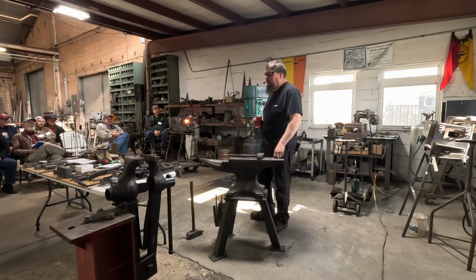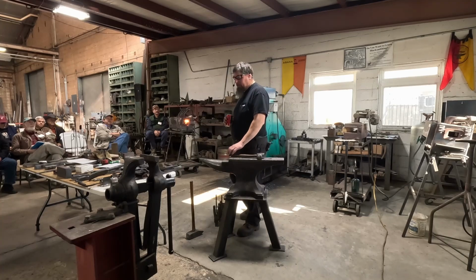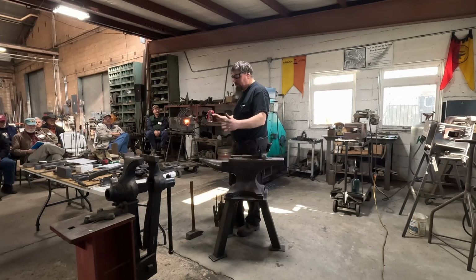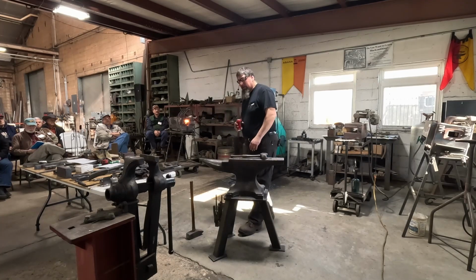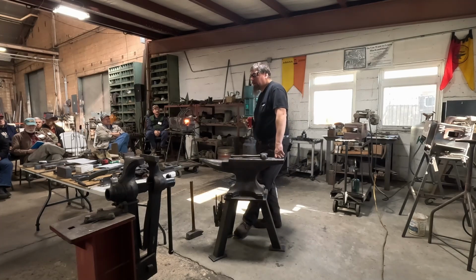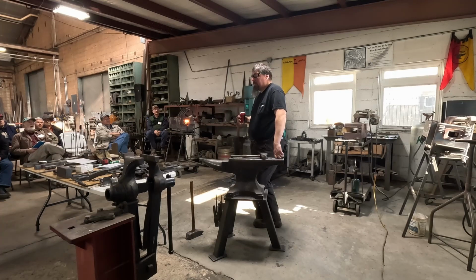So when we're water quenching, we typically keep the water temperature under 100 degrees Fahrenheit. So if your quench is so massive that you're going to get your water hotter than that, then you probably want a bigger volume of water. At work, with the great big massive things that we do, the quench tanks in the shop that I work in, we have two of them, and they're both 50,000 gallon quench tanks. They're big, they're like swimming pools. One of them is filled with water, the other one is filled with a water-soluble polymer quench fluid.